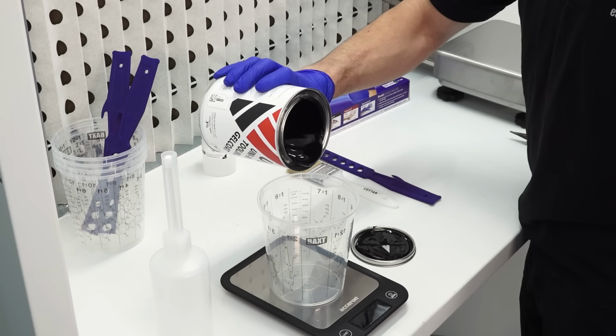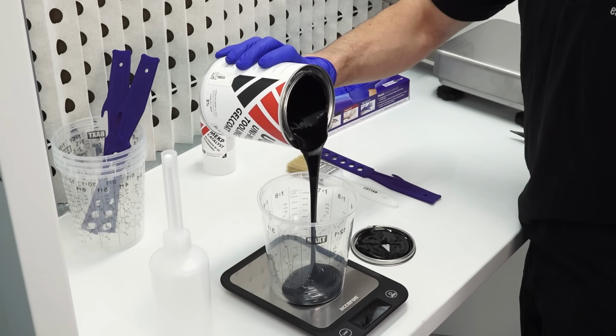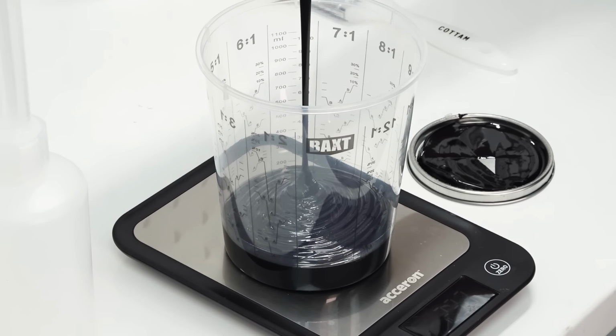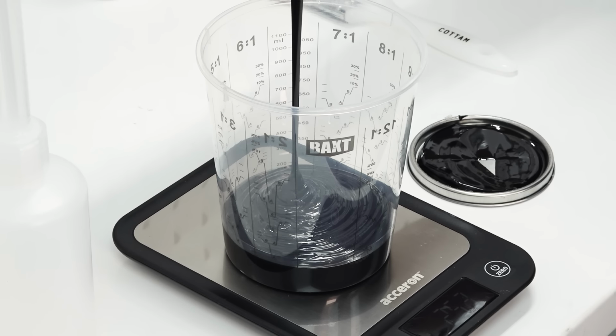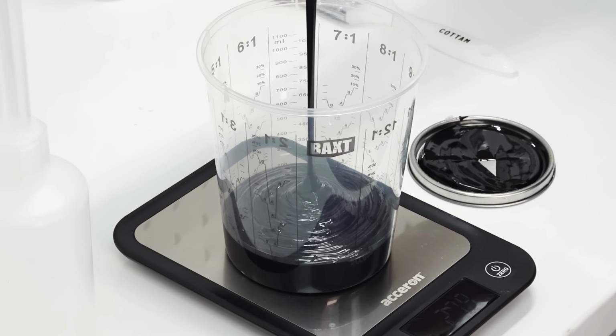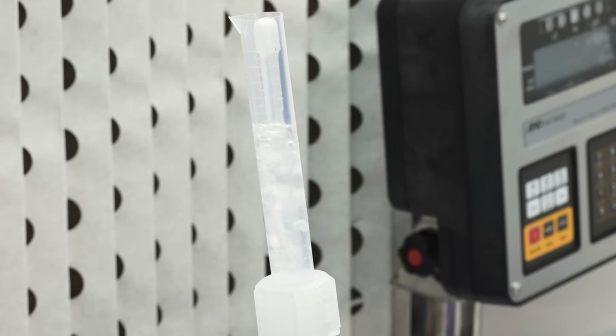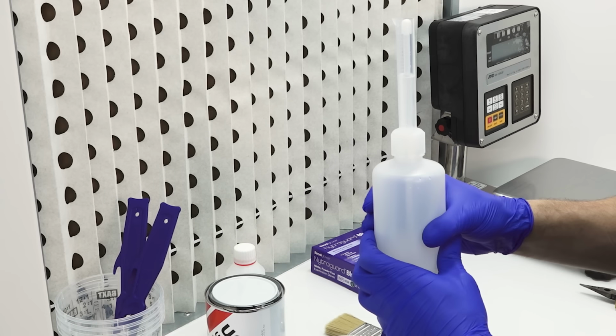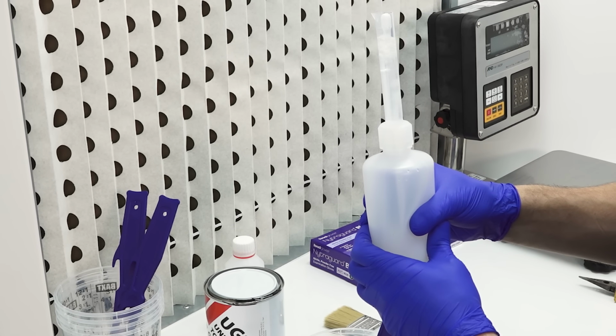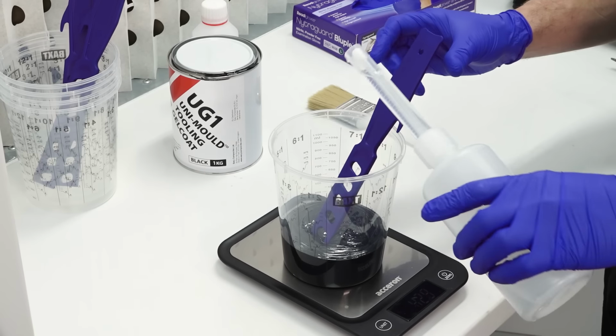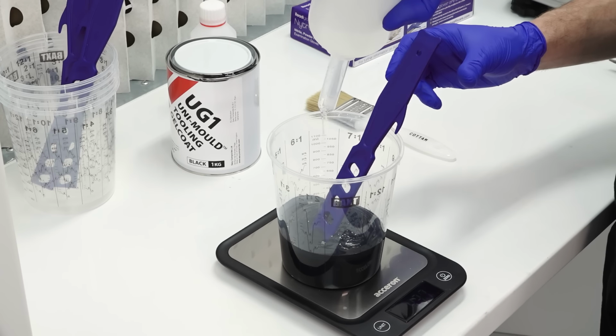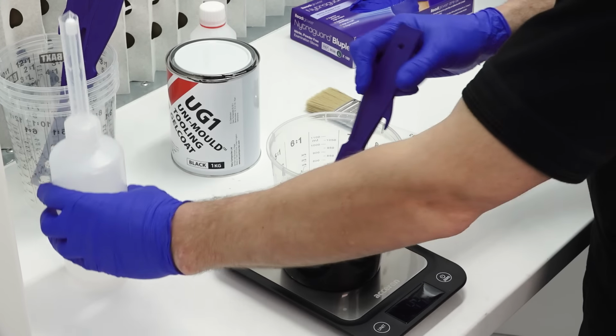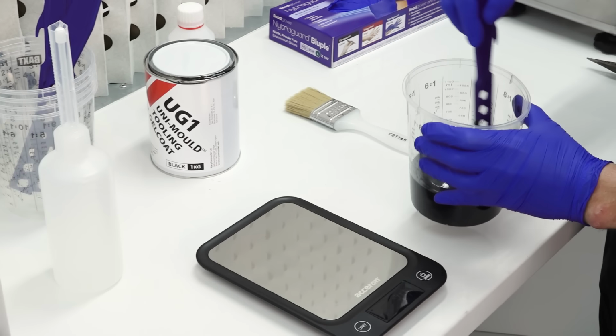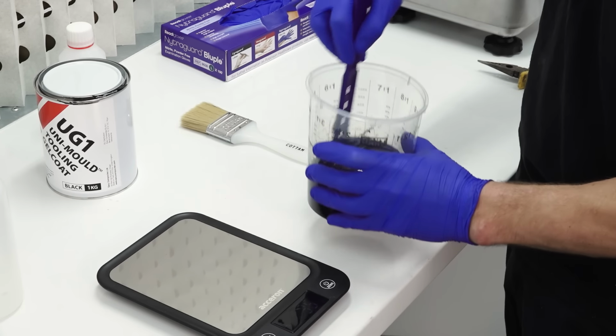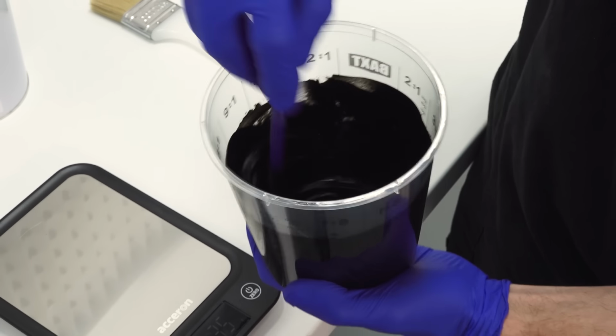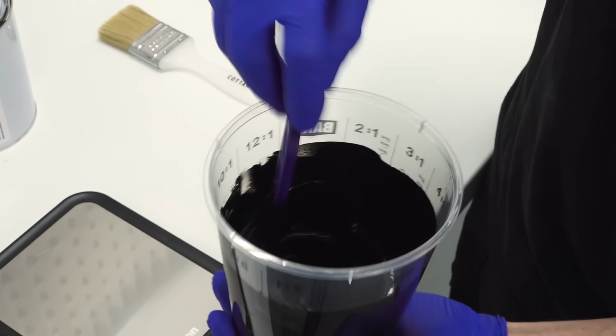The gel coat forms a hard-wearing, polishable and airtight surface to the mould. In most cases, this gel should be applied in 2 even coats to ensure a complete thick coverage. You will need around 500 to 700 grams of gel per square metre per coat. This is weighed out and the MEKP catalyst is added. Under-catalysing here is more of a risk than over-catalysing with this gel. Generally, I use 3% when working at 18 to 20 degrees C and reduce this to no less than 2% when working closer to the maximum 25 degrees C.